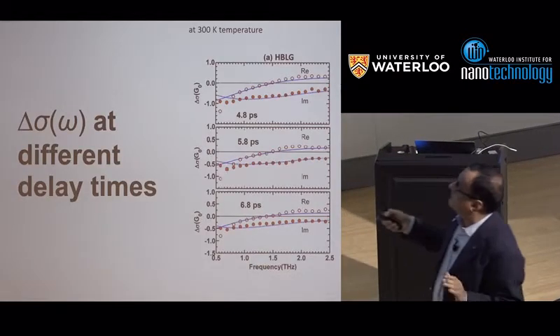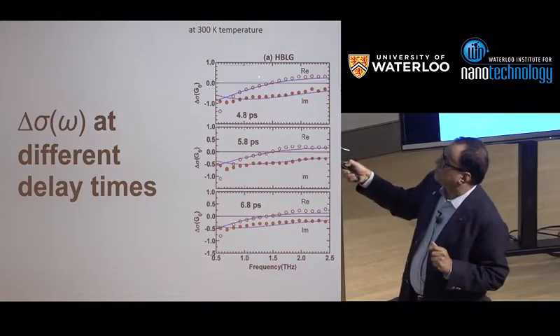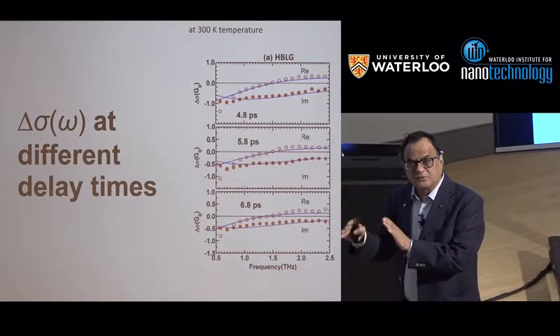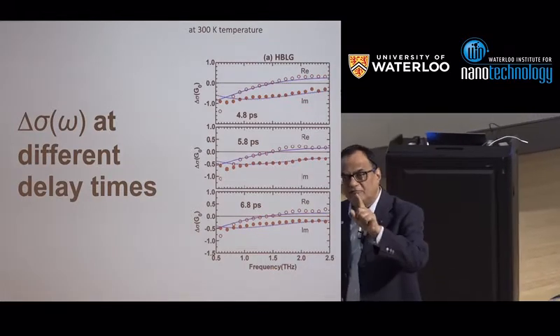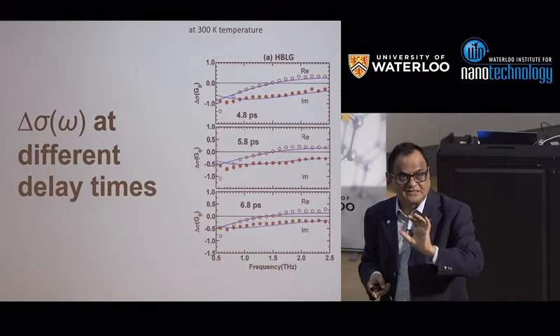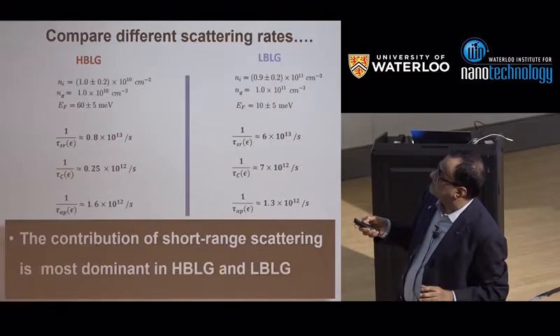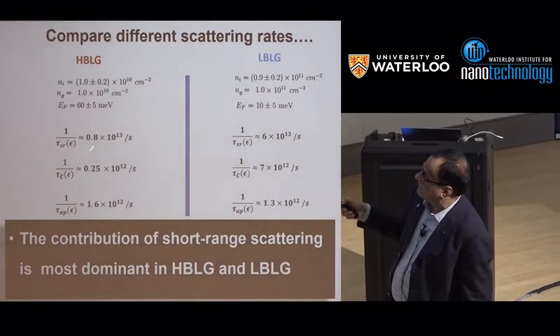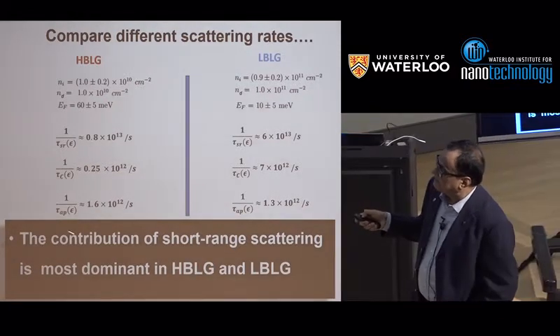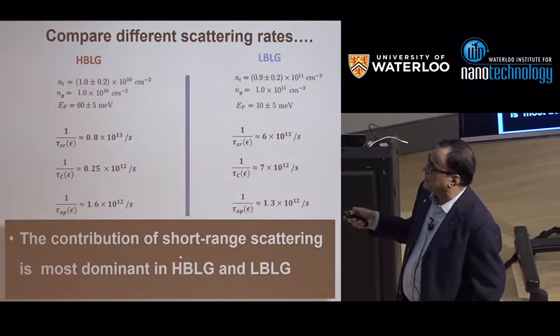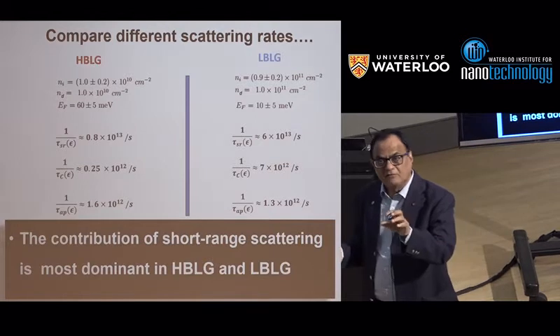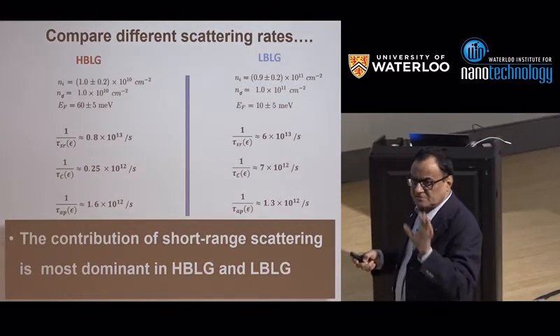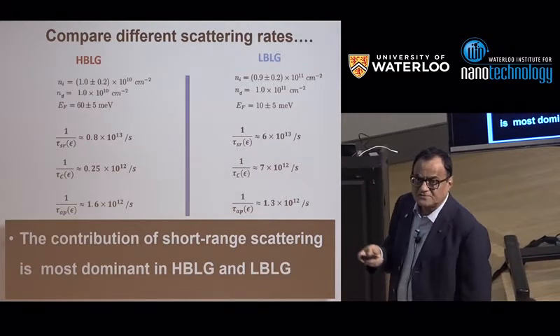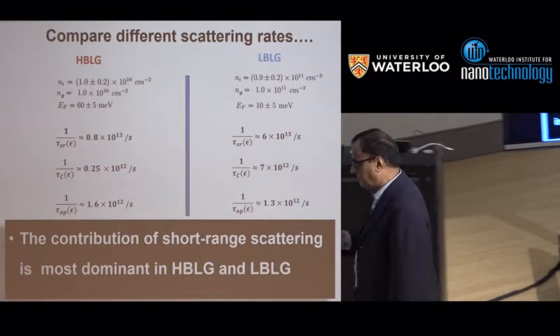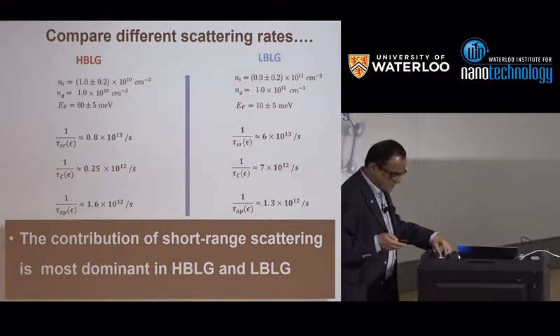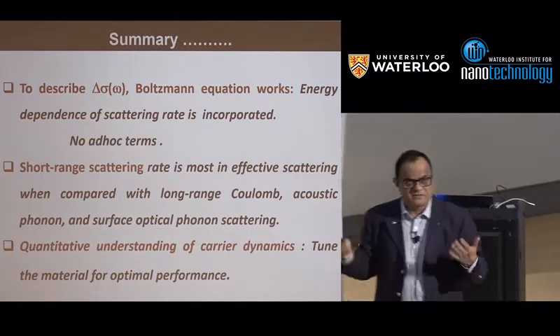And the same thing happens when you vary the delay time. So the experimental data has to be consistent with this calculation only with one set of disorder density. At the end of the day, we realize that we can have quantitative numbers on these parameters, and it also tells us that in bilayer graphene, the maximum contribution is coming from short range scattering of the carriers from these defects and disorder, which is mostly the ripples and so on. So this was satisfying, and it works for single layer and it works for graphene and so on. I will not give you the single layer results because that is again a similar line.